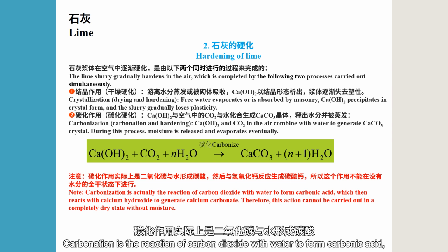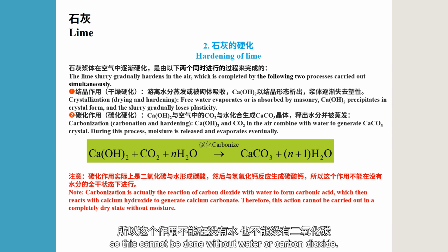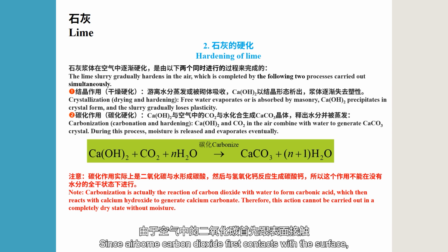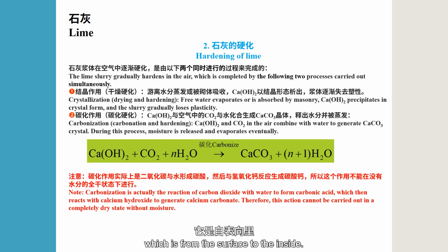Carbonation is the reaction of carbon dioxide with water to form carbonic acid, which then reacts with calcium hydroxide to produce calcium carbonate. So this cannot be done without water or carbon dioxide. Since airborne carbon dioxide first contacts with the surface, the characteristic of the carbonation is just opposite to crystallization, which is from the surface to the inside.